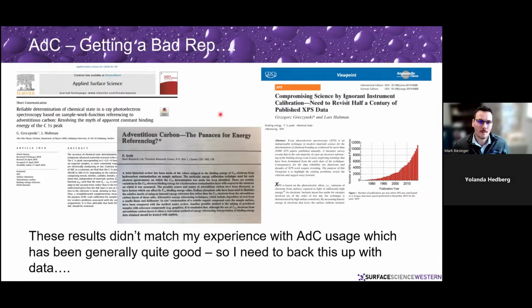So adventitious carbon. And this is where some of this comes from. There's a group out of Sweden, Gregor Greczynski and Lars Hultman, that have put forward a number of papers talking about how adventitious carbon, we shouldn't be using it. It doesn't work. When they first started, they had some fairly sensationalistic titles that came out. Things like compromising science by ignorant instrument calibration, a need to revisit half a century of published XPS data. I have to say it did ruffle some feathers in the XPS community, particularly myself. It didn't jive with what my experience was.